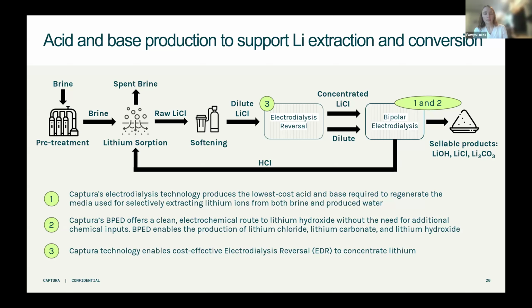So the two areas in which we can really plug in the electrodialysis stack here, one is actually utilizing the brine stream to make an acid and base, which then can be used, the acid would be used to regenerate their sorbent materials. And the base then could be used in multiple other parts of the process, or we could combine this with this other option, which would be to actually use our electrodialysis system to convert the lithium chloride into a more useful end product of lithium hydroxide. So those are the two applications, briefly going over them, in the lithium extraction world.